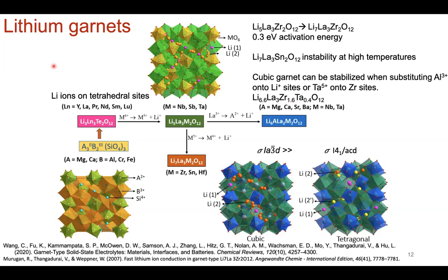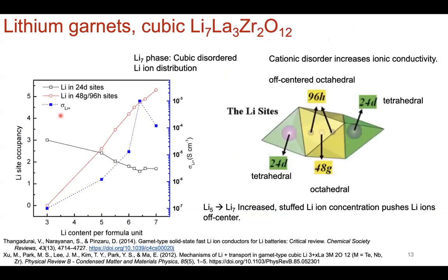Okay. So here, both compositionally and crystal structure wise, when you have lower content of lithium, let's say lithium-3, these lithium ions sit on tetrahedral sites. As you increase your concentration of lithium, you're pushing now the lithium ions to also occupy octahedral sites and even off-centered octahedral sites and tetrahedral sites. So what do I mean by that? Here, as you increase the lithium concentration, you have occupation of these tetrahedral sites, but then more increasingly going from 5 to 6 to 7, the lithium ions that sit at this octahedral site, what's normally this 48G, so the multiplicity is 48, also get pushed out to this off-centered, what's called 96H Wyckoff positions.